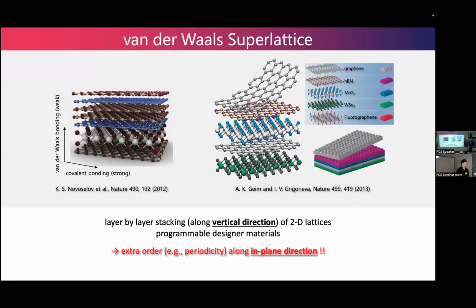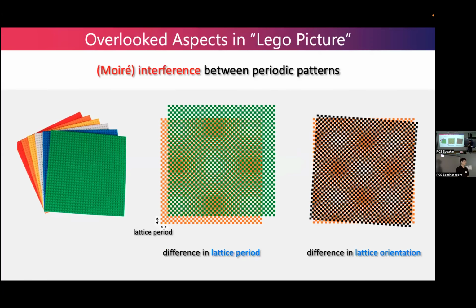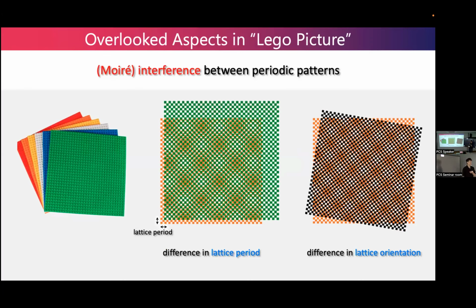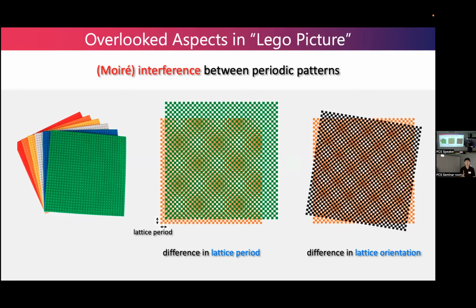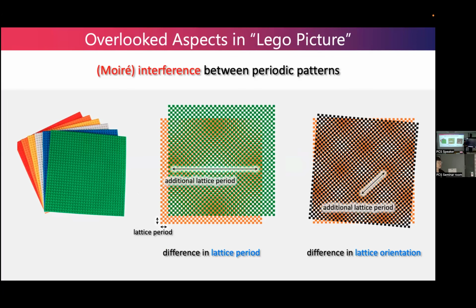With the discovery of graphene and two-dimensional materials, we can make a new kind of superlattice by stacking them along the vertical direction. This unique structure enables us to make an extra order along the in-plane direction, because whenever there is a difference in lattice period or lattice orientation, there always arises an extra periodicity, which we call the moiré interference pattern. The period of a moiré pattern is much longer than that of the constituent materials, so it allows us to access physics far beyond the limit of conventional materials.